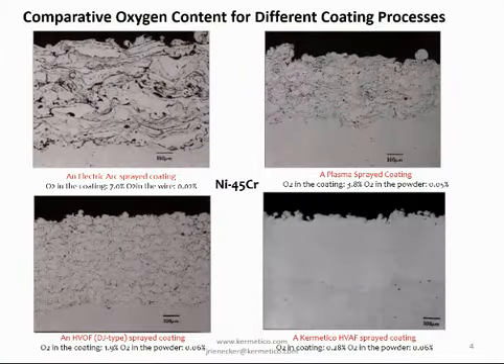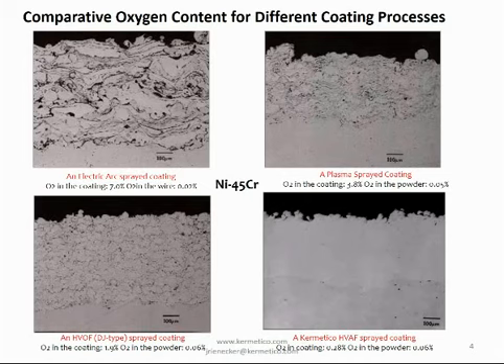Here we have an interesting comparison of nickel chrome applied by an electric arc, a plasma gun, HVOF DJ type, and our HVAF process. What's been studied via X-ray diffraction is the oxygen content in the original feedstock material compared to that in the finished as-sprayed coating. Electric arc was 0.02 percent; it's a wire, so you'd expect the oxygen level to be very low, but the as-sprayed coating had 7% oxygen, and that shows up in the micrograph.